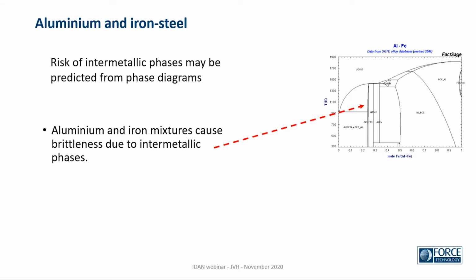An example: if we try to weld aluminium and iron or steel, we have a high risk of intermetallic phases. If we do it theoretically, we could go to phase diagrams and see that this combination of metals has areas where we have these intermetallic phases. So we can predict that if this is the combination range that we are in, we might get problems. And these phases are causing brittleness in the weld metal.